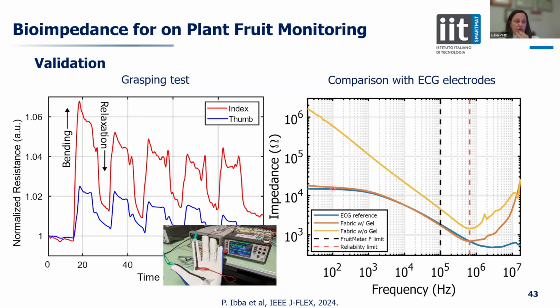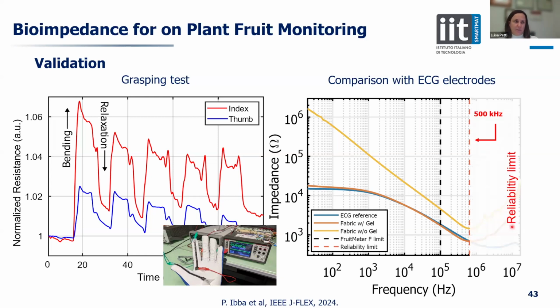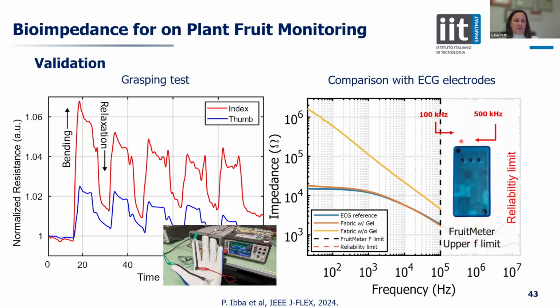So you see that the fabric with the gel is very close to the ECG, although only up to a certain frequency. So there is a reliability limit which needs to be taken into account, but this is okay because the upper limit of frequency measured with this portable impedance analyzer is 100 kilohertz.